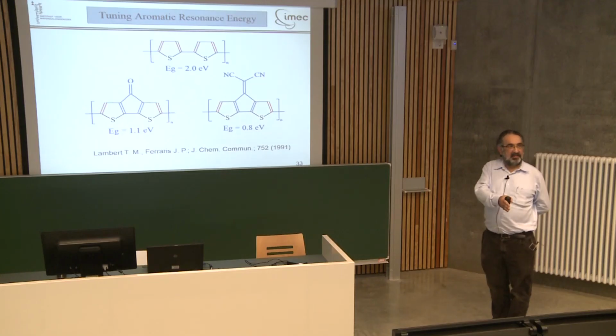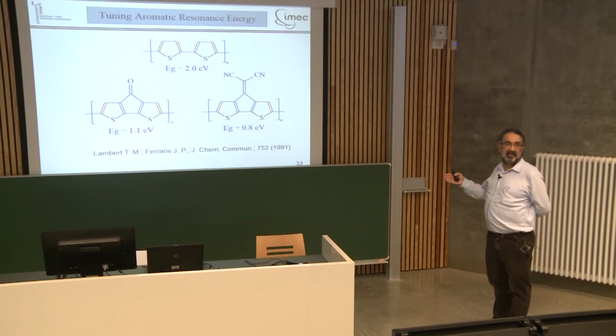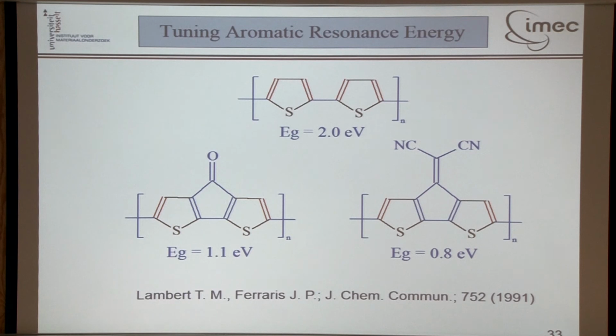Besides aromatic systems, you have also anti-aromatic systems, in which a ring structure leads to destabilization. And this part here is anti-aromatic. So you combine 2 aromatic structures with an anti-aromatic one. Also here you have that. And so globally the aromaticity is brought down, so your band gap will decrease.